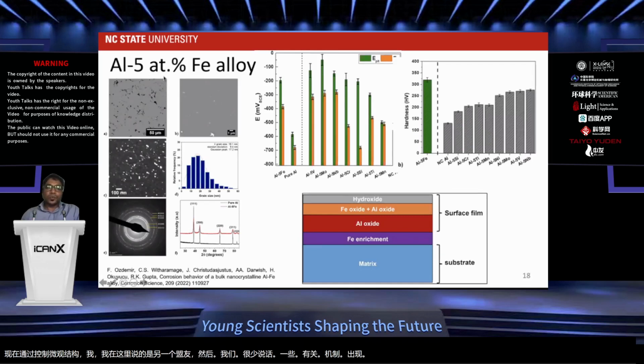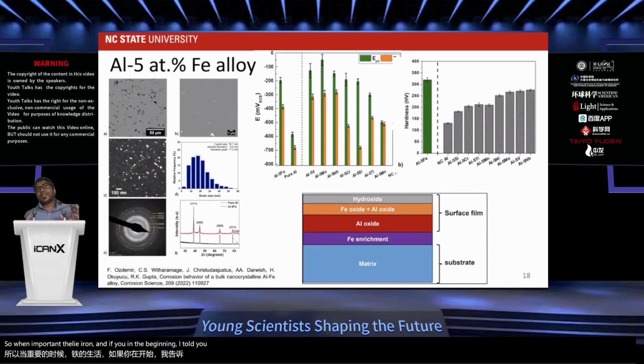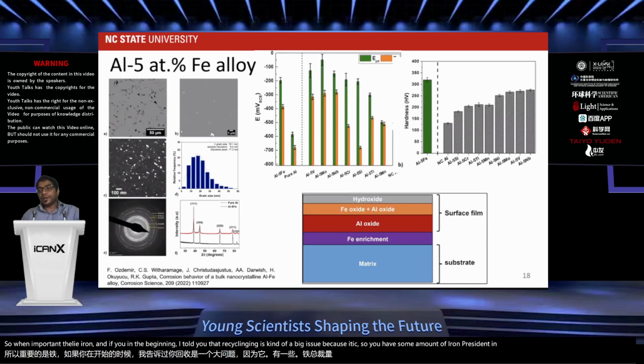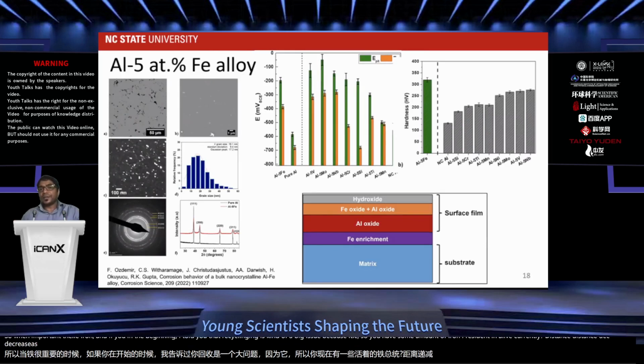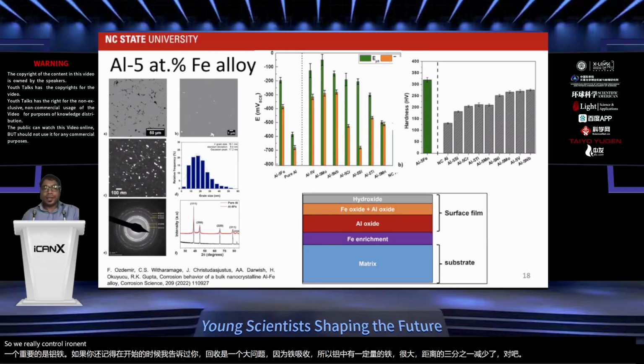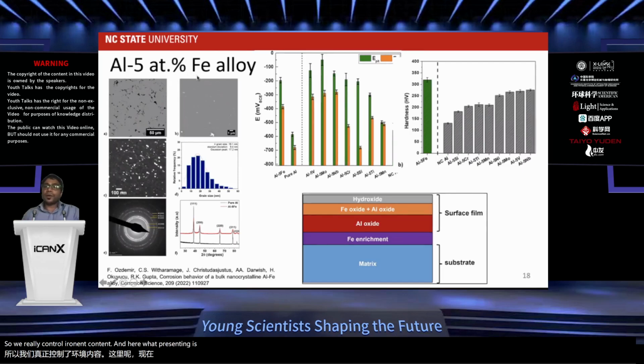Now I'm talking about one more alloy here, and then we talk a little bit about the mechanisms too. So one important alloy is aluminum iron, and if you remember in the beginning, I told you that recycling is a big issue because of iron uptake. So you have some amount of iron present in aluminum alloys, and corrosion resistance decreases, right? So we really want to control iron content. And here what I'm presenting is 5 atomic percent iron, right?